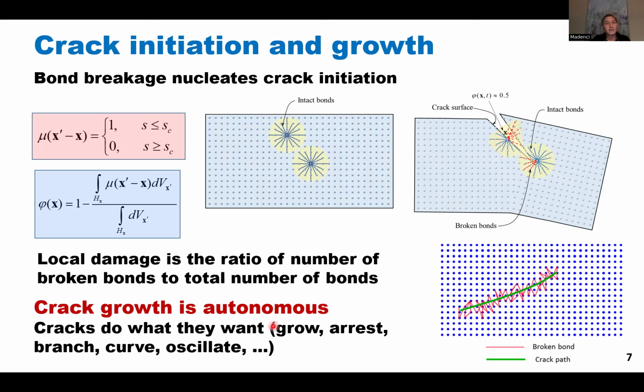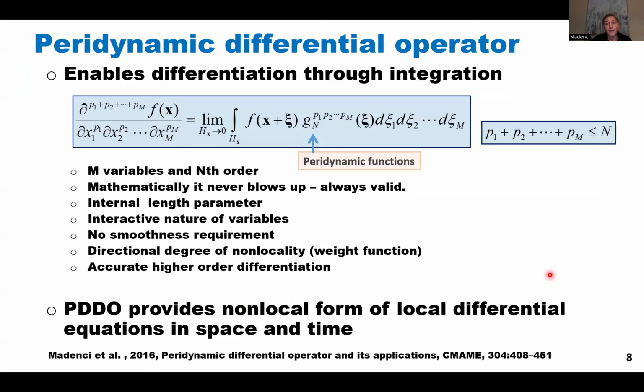And in peridynamic theory, the crack growth is also autonomous. So basically, we apply this particular criterion here to break a bond, and the rest is the same. So if the crack is going to go, if it's going to oscillate, if it's going to branch, if it's going to arrest, it's autonomous. So we don't control that. We don't guide how the crack should grow. And so that was 2007. That's the peridynamic theory Stewart-Silling introduced.